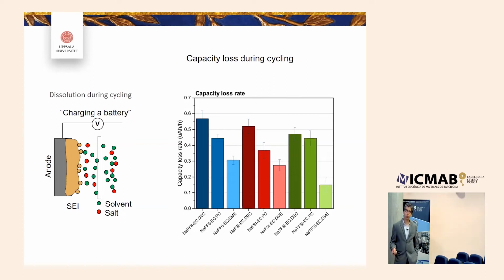But we can see also for the same solvent, there is influence by the salt. So for example, if you go for ECDME, we can see that there is a difference between TFSI, FSI, or PF6. TFSI in ECDME is giving the lowest capacity loss due to SEI dissolution.